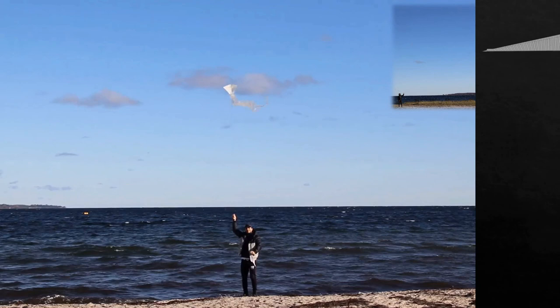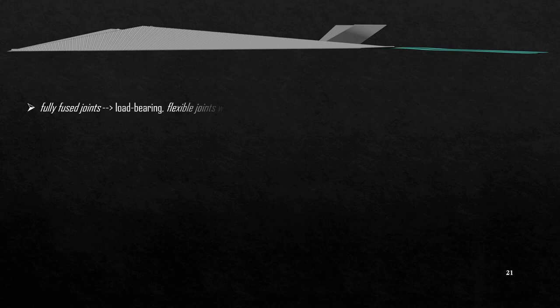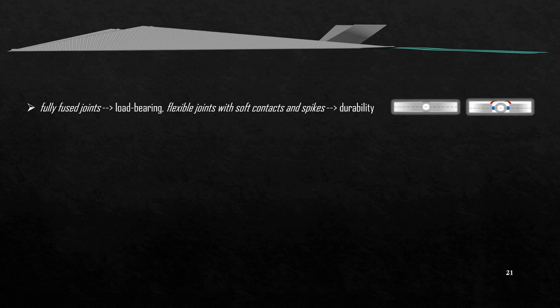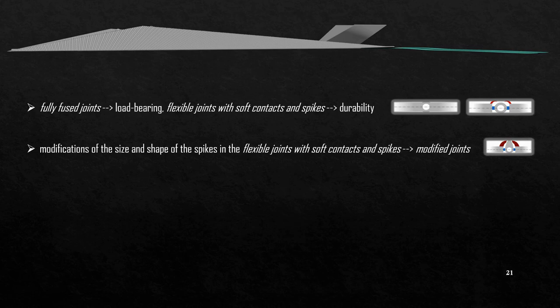Well, to sum up our findings in this study, we could say, while the 3D printed fully fused joints were suitable for load-bearing purposes, the 3D printed flexible joints had the best durability. A slight modification of the size and shape of the spikes on the flexible joint with soft contacts and spikes resulted in a balance between load-bearing capacity and durability in the modified joints.